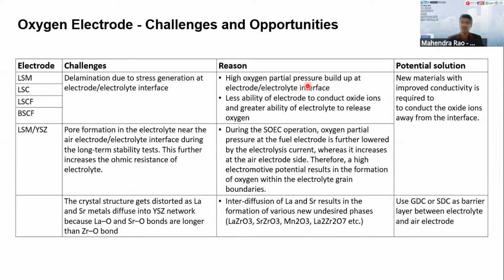For the oxygen electrode, we prefer to use perovskite-based material as the main selection, as highlighted by Prof. Kawada. So we know there are some issues such as delamination due to the stress generation between the electrode and electrolyte. This is actually high oxygen partial pressure building up at the electrode interface when it is in electrolyzer mode. So there is less ability of the electrode to conduct oxide ions and greater ability of the electrolyte to release oxygen.